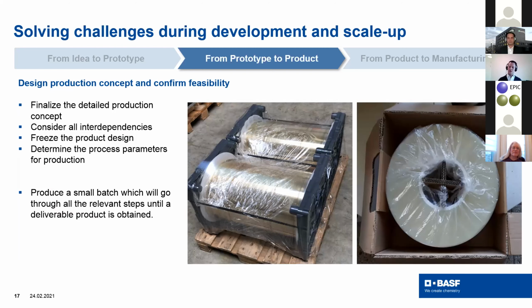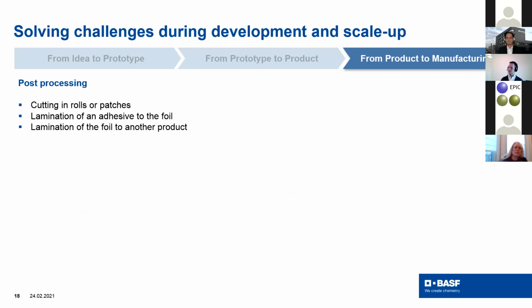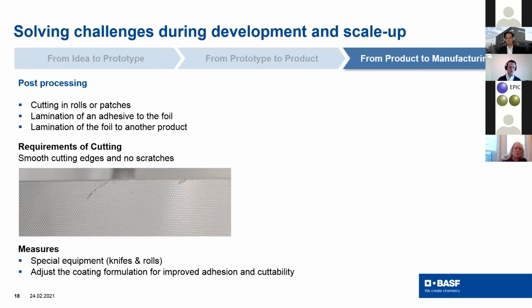And we try to come to a point really until the end, until the packaged product which we want to send to a customer. And one of the things I want to show you: of course, at the beginning, you don't think it can go wrong. We, of course, did small samples and stuff like that, but we had a small problem at the post-processing. Post-processing is, for example, cutting the rolls or patches, laminating adhesive to the foil, etc. And we did some initial tests, everything looked fine. And then you start your scale up. And then you see that a certain amount of the rolls have cutting defects. Of course, you want smooth cutting edges and no scratches. And here you see some scratches, you see some coating defects.